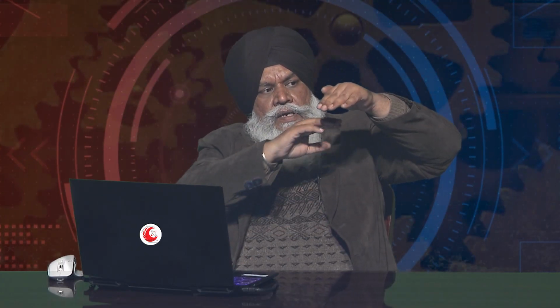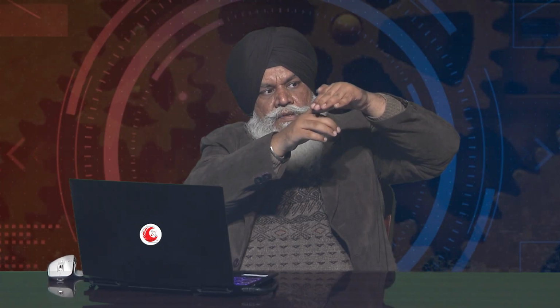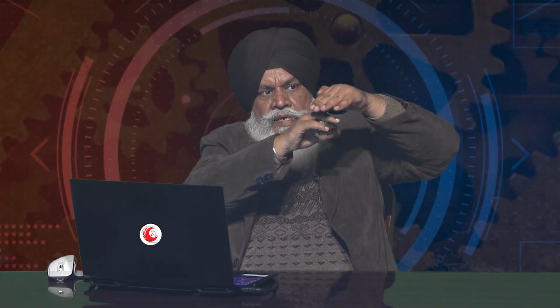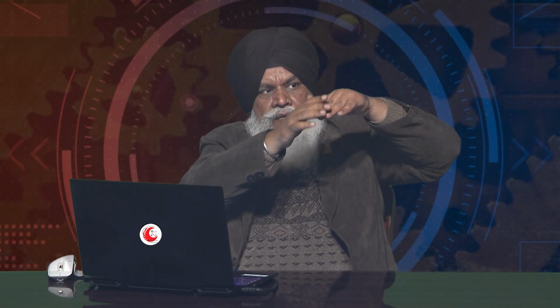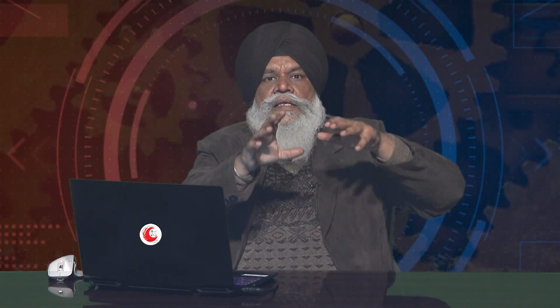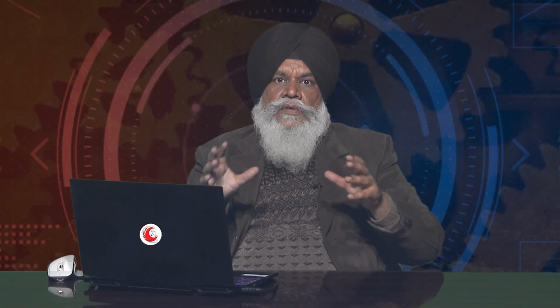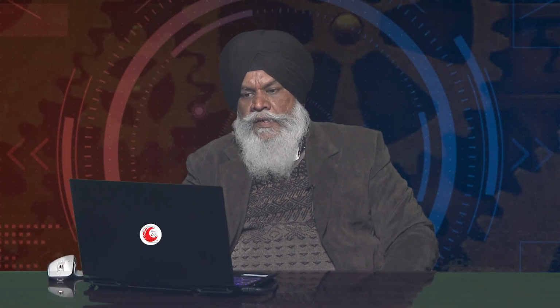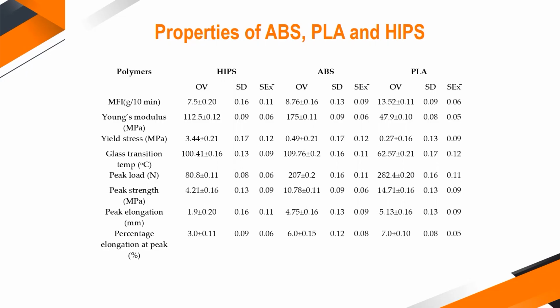Now, if the whole material is a single composite, it will definitely fail. The better solution can be if I put a material with better compressive properties on the downside, and a material with better tensile properties on the top side, and then I assemble. So that is the idea of using these three materials over here. We used HIPS, that is high impact polystyrene, ABS and PLA, and they have a significant difference in their melt flow index. You can see the observed value here is 7.5, with the standard deviation and standard error shown in tabular form in front of your screen.